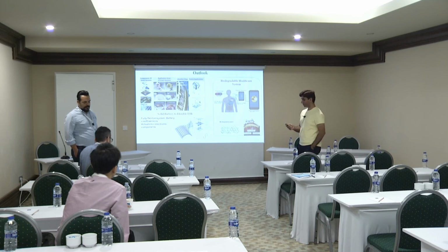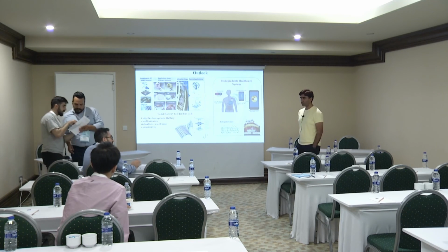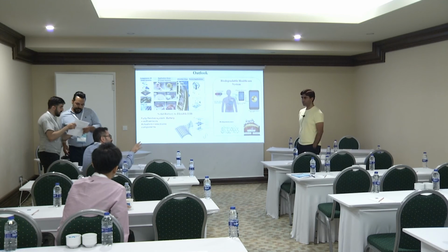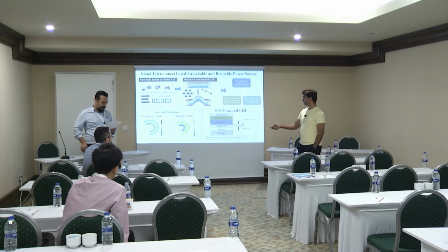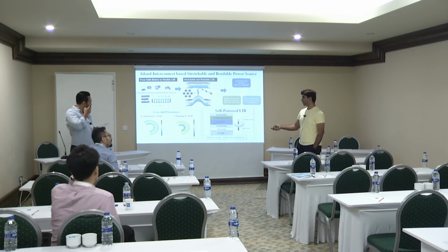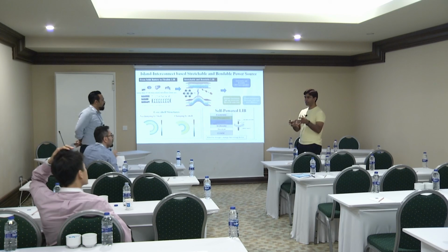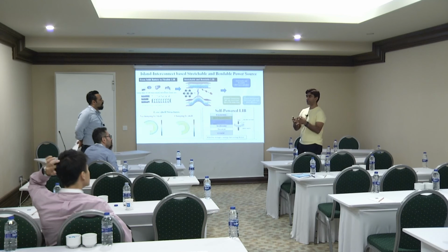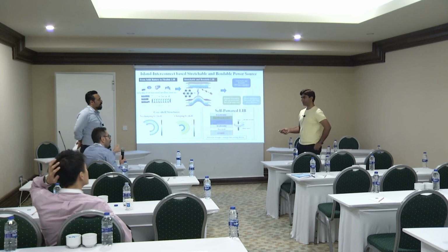The second question is related to the silicon cracking issue. I know that there are recent articles saying that if you create a surface oxide on purpose, like a core-shell structure, silicon and then silicon dioxide. Yeah, I will show you. It's a very good point. Here, you can see. The mechanism is clamping. If you have a shell, you will have clamping, so that shell can help hold the expansion. But it has issues of low capacity and cyclic life. So it lowers that. Okay, substantial.